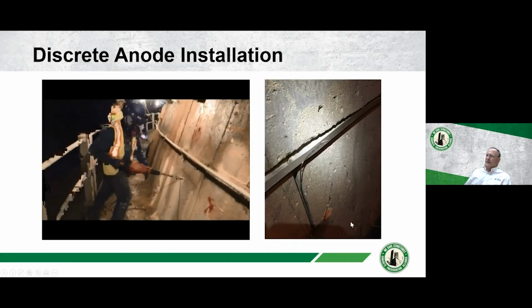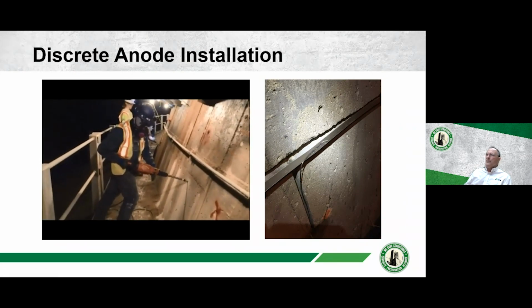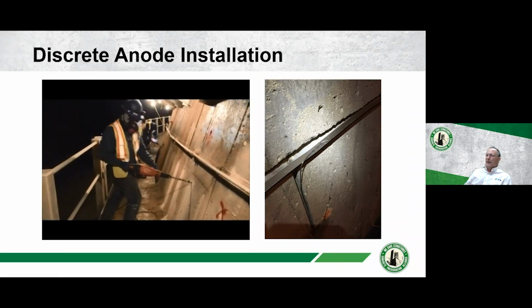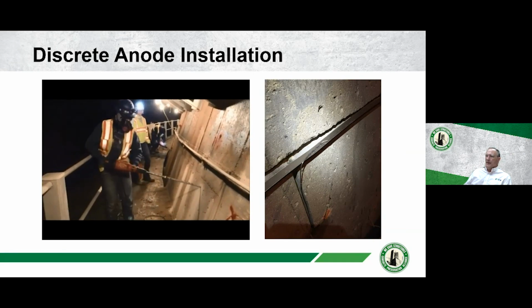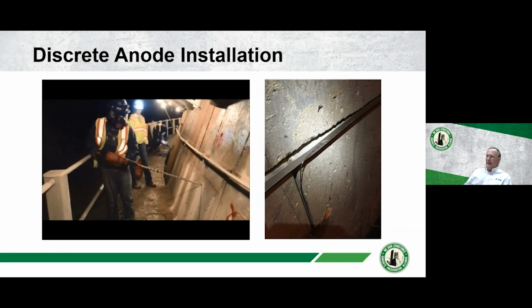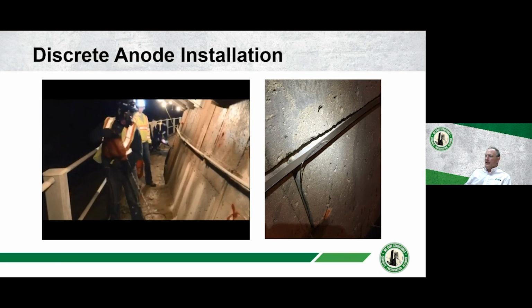And here's just a video from the installation. You can see they went in quite a ways to get the anodes installed. This is a close-up of the current distributor bar and the titanium anode wire being welded. You see how it's spot welded at multiple locations? That's how we do it.